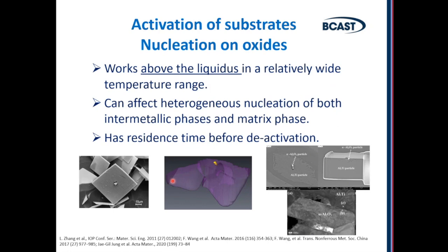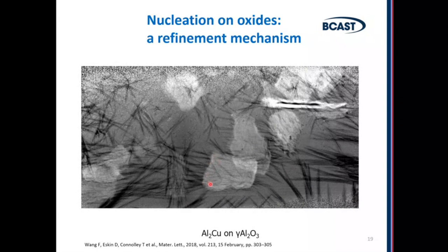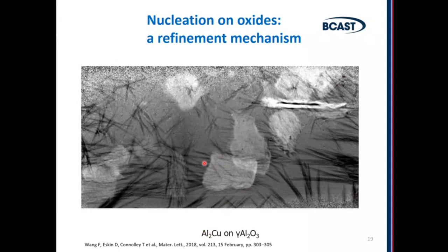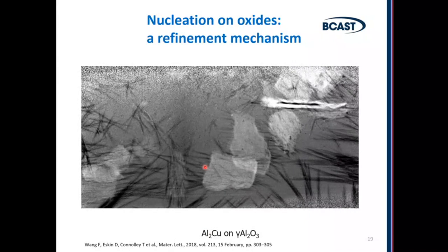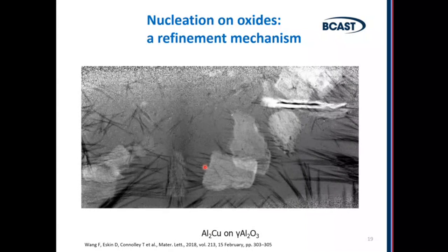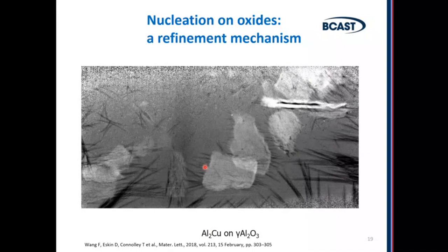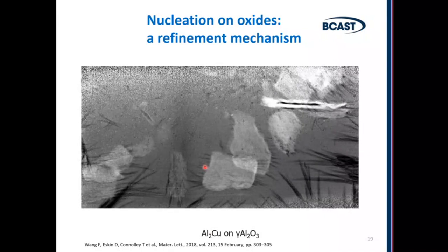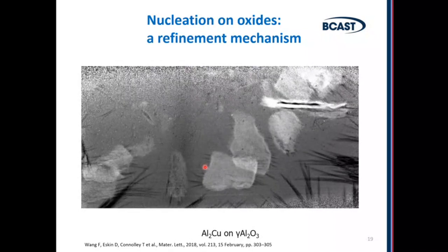Activation of substrates is very difficult, of course, to observe and prove experimentally, but indirectly we can say that very frequently, if we treat our melt above the liquidus in a relatively wide temperature range, and then solidify the material, we frequently find oxide inclusions inside intermetallics, which indirectly shows that these intermetallics were nucleated on these oxides. We also have very interesting evidence from synchrotron studies where we see that intermetallics of aluminium-copper are nucleated on oxides, on aluminium oxide, after this melt was processed with ultrasound. So this is direct evidence of nucleation on oxides. And if there is no cavitation treatment before, these oxides will be inert, they will not be wetted by liquid aluminium, and so there will be no nucleation.